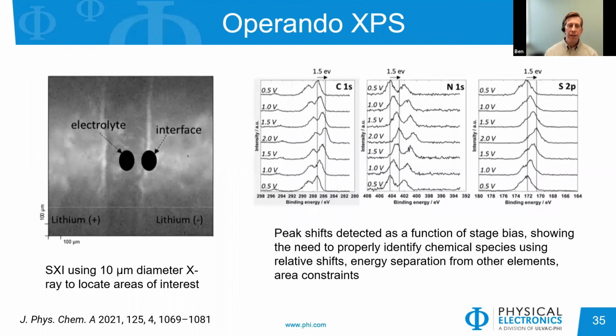And this is just a last example of using an operando XPS. In this case, we have, I believe, an electrolyte material with lithium foil up against it. Again, we're using the SXI, which is our secondary electron imaging, to determine exactly where the electrolyte material is versus the interface. And so we can see that and then drop points to analyze those two locations, also biasing the sample at the same time.